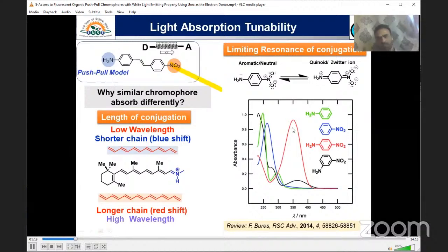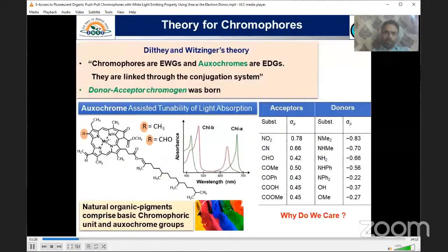In this graph, you can see the position of the donor and acceptor groups has a huge impact on the absorption spectra of the molecule. Basically, Dilthey and Witzinger came up with the theory of chromophore and auxochrome. They said that chromophores are electron withdrawing groups and auxochromes are electron donating groups. Donor-acceptor molecules are colored because of the presence of newly formed HOMO-LUMO orbitals, whose electronic shift lies in the visible region of the spectra. That's why they are colored.